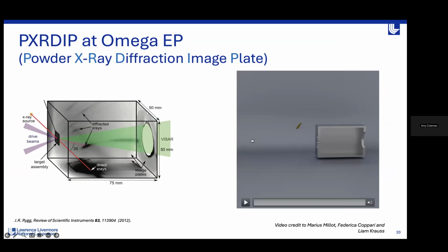At the Omega EP facility, we are collecting our diffraction data using PXRDIP, so this is powder X-ray diffraction image plates. The way that it works is we have our target, so our multi-layered ablator sample window target, sitting on the front of the PXRDIP box. A laser drive comes in, and this is what launches the compression within our target. During the entirety of the experiment, we have another laser coming in and looking at the rear surface of our target. I'll talk in a bit more detail about this in a moment, but this is our VISAR diagnostic. This is something that we measure velocity with, and it's one of the ways that we infer pressure within our experiments. And then the other thing we have here is our X-ray source.